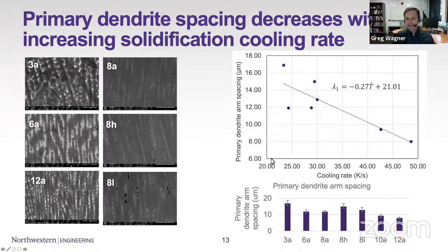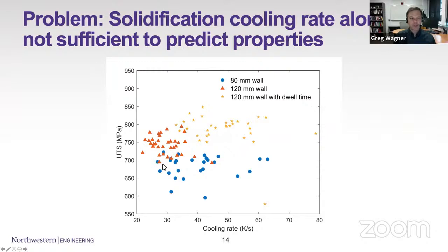And so we can see that our predicted cooling rate tracks fairly well with the primary dendrite arm spacing. Again, as you might expect, as the cooling rate increases, the microstructure gets finer, the arm spacing goes down. But when we try to relate that cooling rate to the UTS for all of the points that we have, it's a lot harder to tell this story, right?